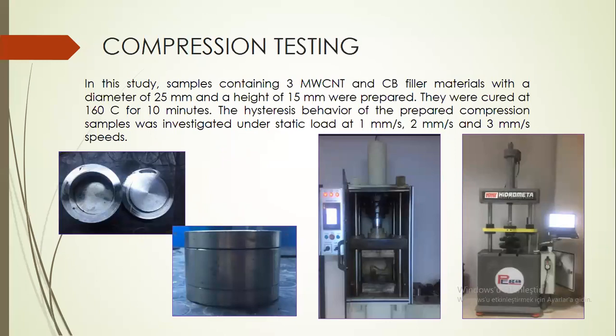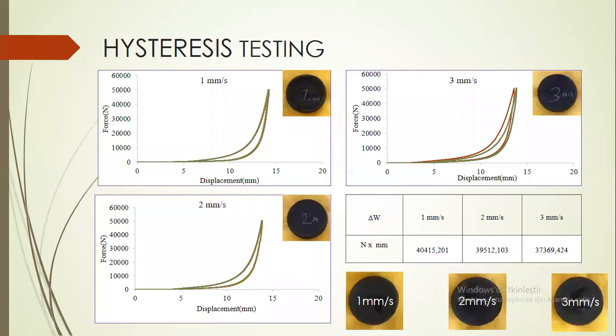In this study, samples containing 3 MWCNT and CB filler materials with a diameter of 25 mm and a height of 15 mm were prepared. They were cured at 160 Celsius for 10 minutes. The hysteresis behavior of the prepared compression samples was investigated under static load at 1 to 3 mm per second speeds.